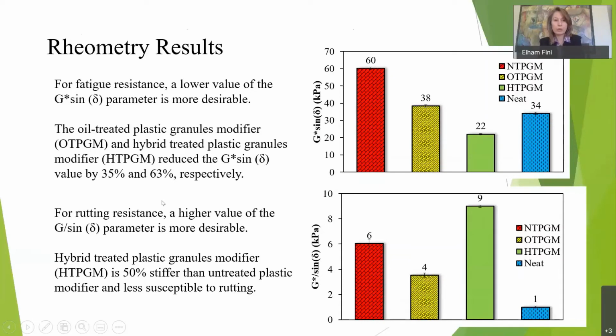So here you can see also another test for the rutting resistance. Well, let me finish this. For the improvement of fatigue, you can see if this is 34, you get 22 here, you get significant improvement in the fatigue. That means based on this measure of fatigue resistance, the one that has oil treatment is a bit worse, but the one that has hybrid treatment is even better in terms of fatigue. It means it lasts more cycles before it cracks. It means more traffic before it cracks.